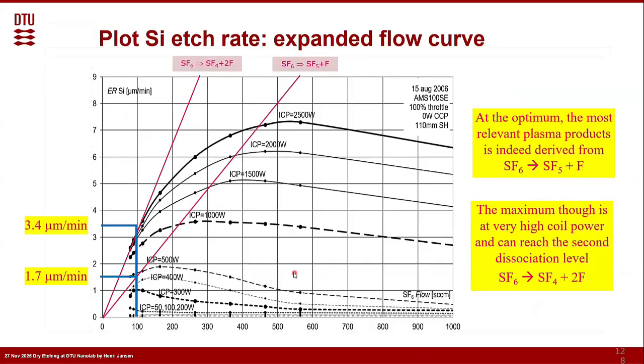Why? We have to look at it: we assumed here that SF6 cracked into SF5 and F. But at higher powers it's not impossible that you dissociate SF6 even into SF4 plus 2F. So what happens at that level, at 100 sccm with very high power, is that we get into a regime where we crack the SF6 more efficiently and create even two fluorine, and therefore you get 3.4. But you see the maximum, where it goes down again at the highest level, that point is 1.7 micrometers per minute.